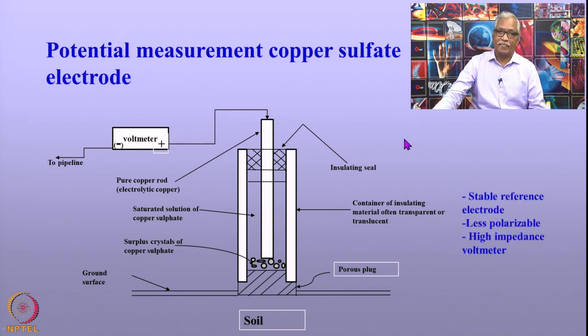The other important characteristics of the reference electrode is it should be stable, it should not disintegrate, it should be less polarizable, which means that when I measure this voltage between the pipeline and the reference electrode, a small current is expected to pass through and that should not polarize the reference electrode. In order to minimize the current passing between this reference electrode and the pipeline, you also use a high impedance voltmeter. The high impedance voltmeter ensures that not too much current flows between this reference electrode and the pipeline because of the voltage difference.